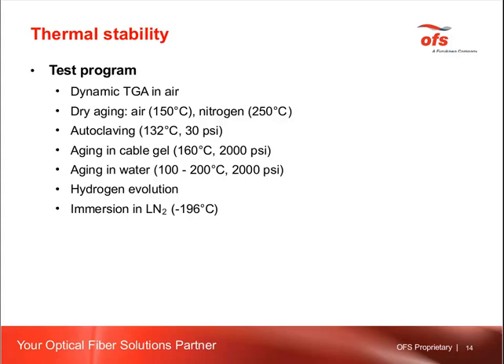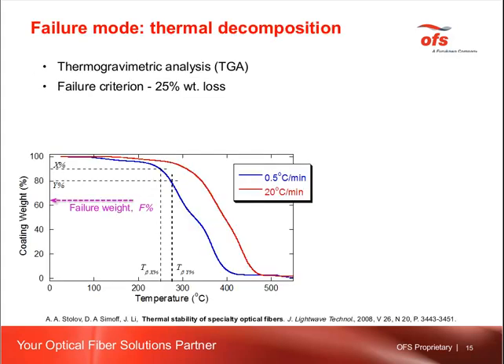So here we applied an extensive test program. First of all, the fibers were tested using dynamic thermogravimetric analysis in air. Then we applied dry aging in the air and in nitrogen. Then the fibers were exposed to autoclaving. Then we used high temperature and high pressure aging of fibers in water and a cable gel. We also tested fibers for their hydrogen evolution. And we also tested another extreme, the low temperatures region. We immersed fibers in liquid nitrogen. I'm going to describe these results to you one by one.